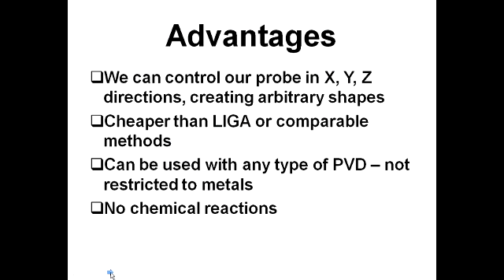Advantages of our idea is that we could control the probe position in X, Y, and Z direction, and by controlling the probe position, we could create arbitrary shapes, not only a rectangle, not only a cube, or a very thin layer. We could control the shape. We could make whatever we like by controlling the position of the probe.